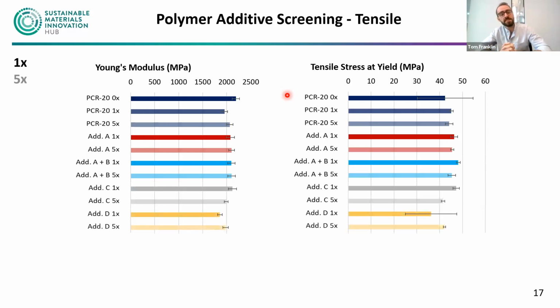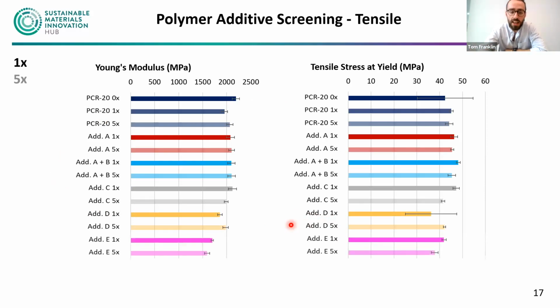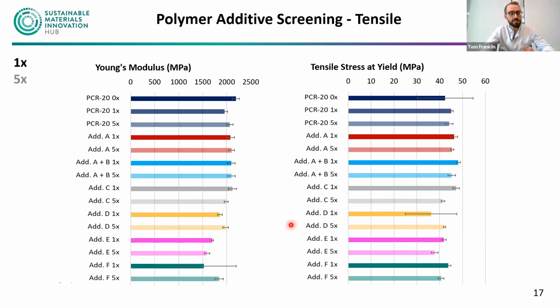Our two mystery additives, again, some fairly subtle changes, not necessarily what we would have expected. Typically, one expects, with more extrusion and more degradation, your mechanical properties would decrease. But certainly for this yellow trace, we're seeing very subtle increases in our mechanical behavior. Quite strange. And lastly, our compatibilizers, again, quite strange behavior. We know that this green one had quite a significant increase in molecular weight. But again, the impact on the mechanical properties does not appear to translate across.